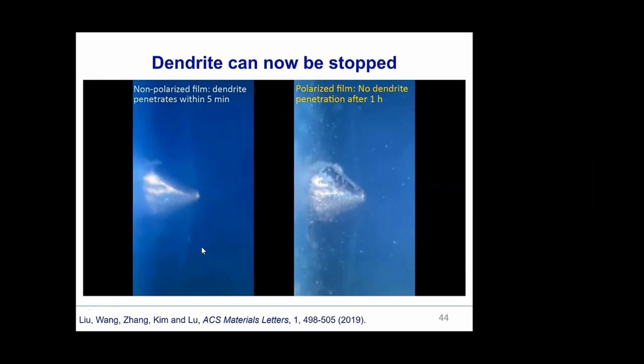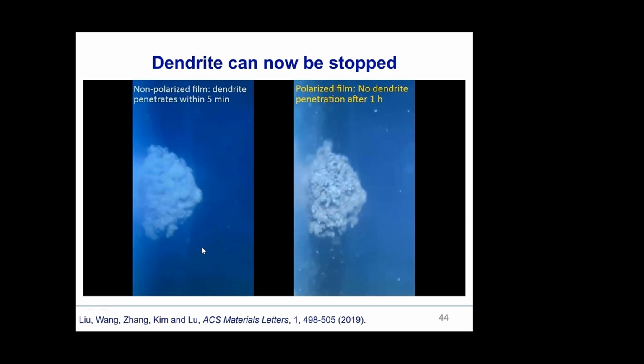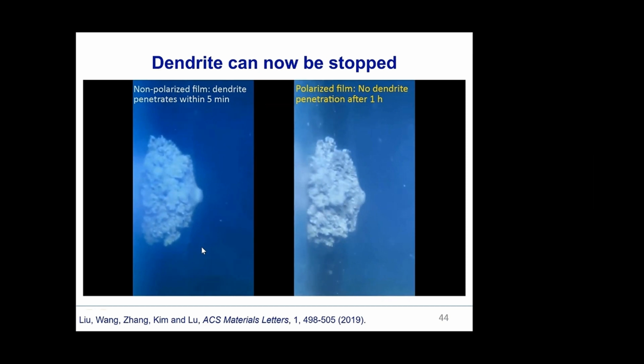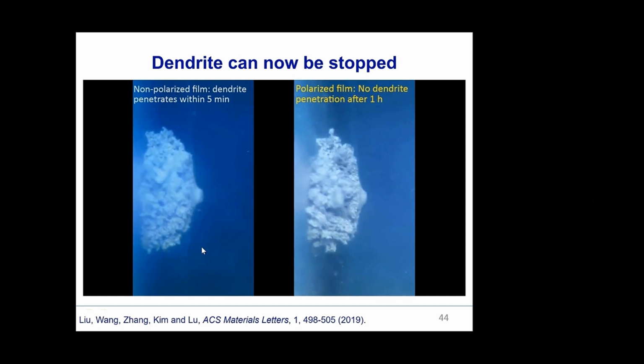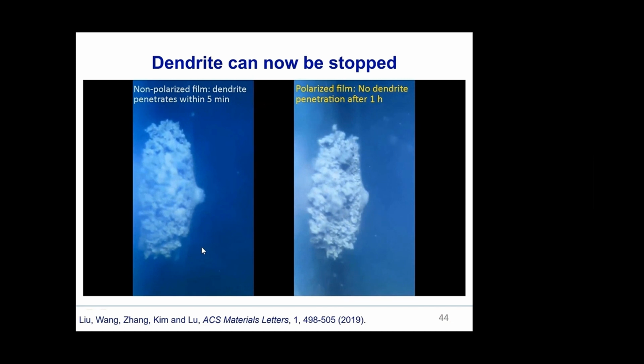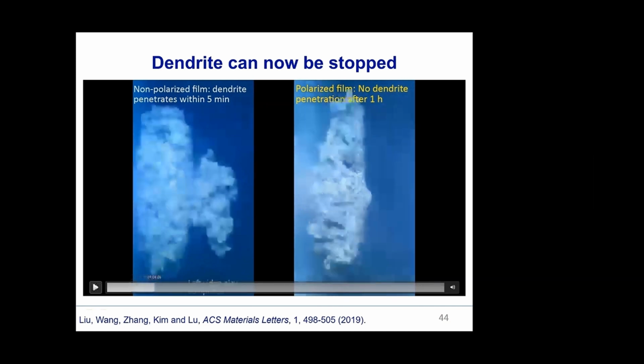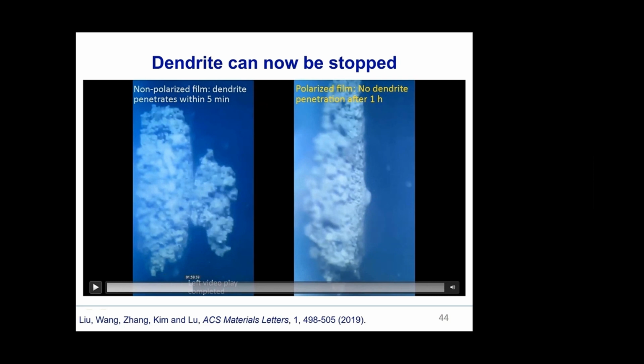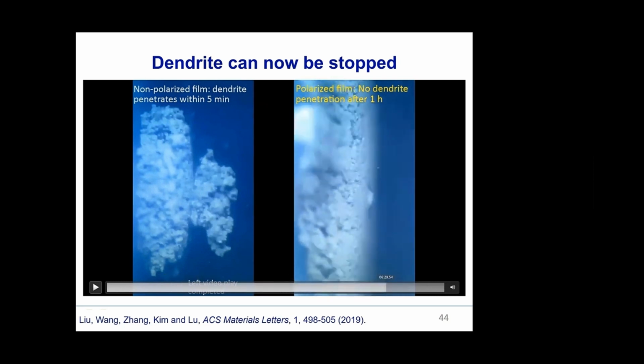Here is a comparison between our approach and a regular separator. On the left is a regular separator. We can observe the dendrite quickly penetrates the separator. Well, for our approach, there is no dendrite penetration after one hour. We can observe the dendrite penetration on the left, and the surface keeps flat for the separator on the right.